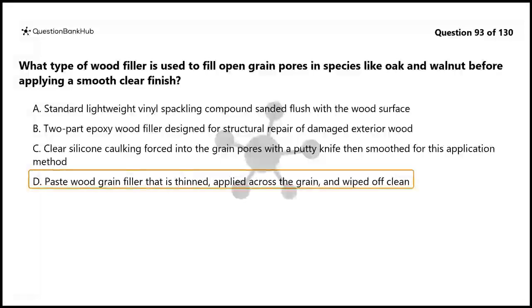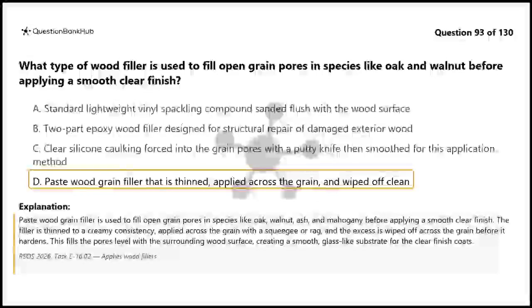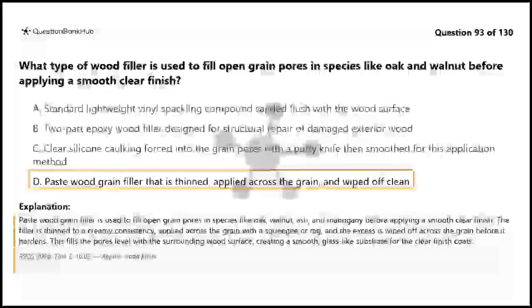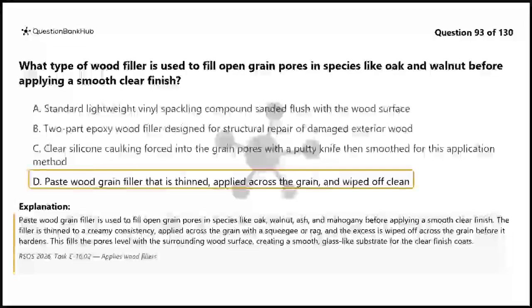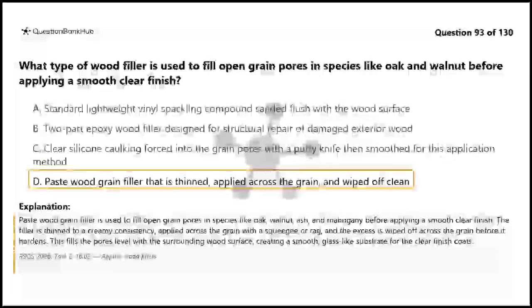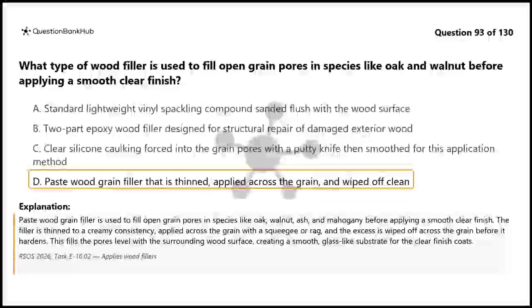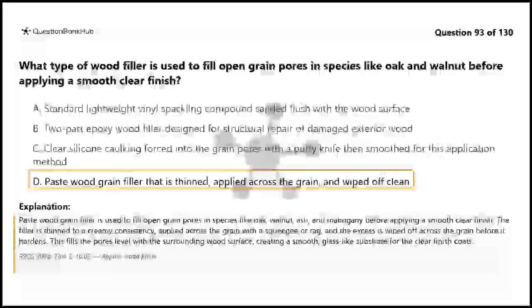The correct answer is D. Paste wood grain filler is used to fill open grain pores in species like oak, walnut, ash, and mahogany before applying a smooth clear finish. The filler is thinned to a creamy consistency, applied across the grain with a squeegee or rag, and the excess is wiped off across the grain before it hardens. This fills the pores level with the surrounding wood surface, creating a smooth, glass-like substrate for the clear finish coats.